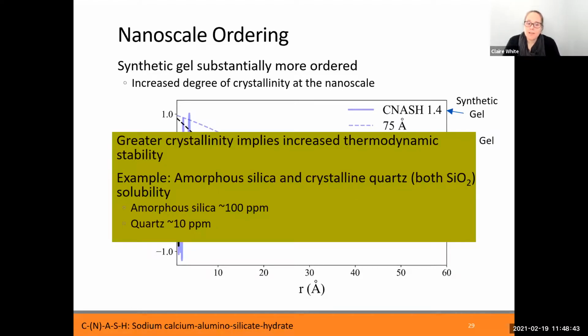The first thing is a greater degree of crystallinity can imply, there's always caveats to this, but can imply increased thermodynamic stability. So say if we're looking at 2 types of silica, amorphous silica versus crystalline quartz, they're both silica, they both have the same local atomic bonding environment, they both have a Q4 silicate network, but if you look at the solubilities, they are different. And so these results for the gels could indicate that there are differences in terms of thermodynamics between the synthetic gels and the real gels, though this is a hypothesis that we have based on these results. And therefore, if we were to confirm or want to investigate more, a lot more research would be needed to either support or contradict this hypothesis that we have.